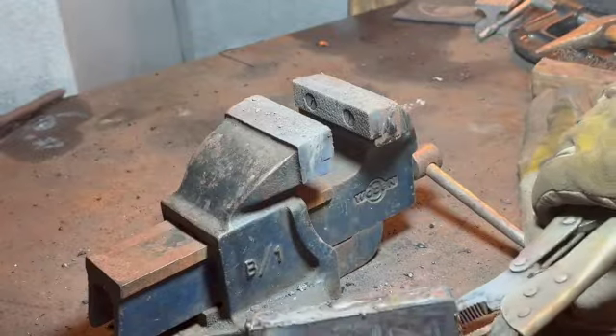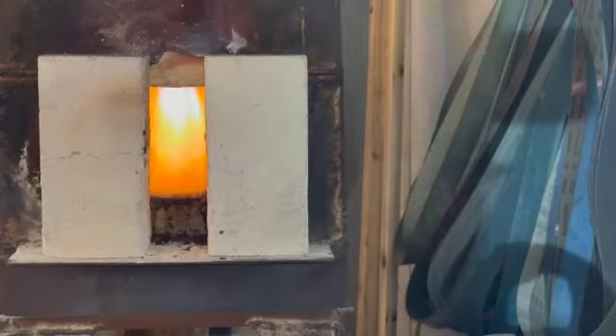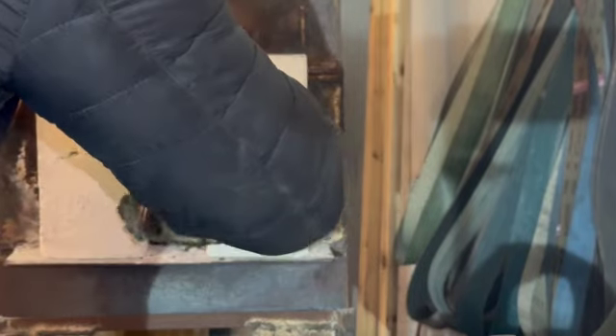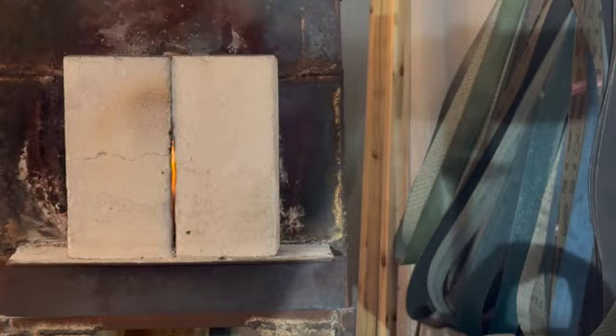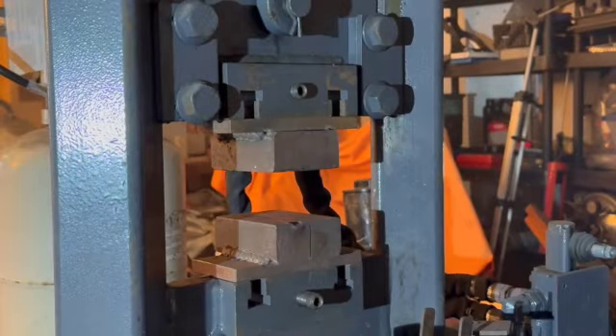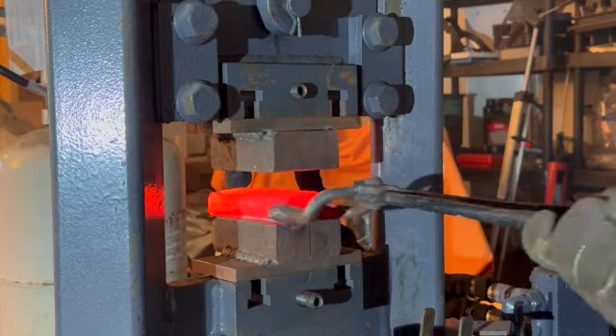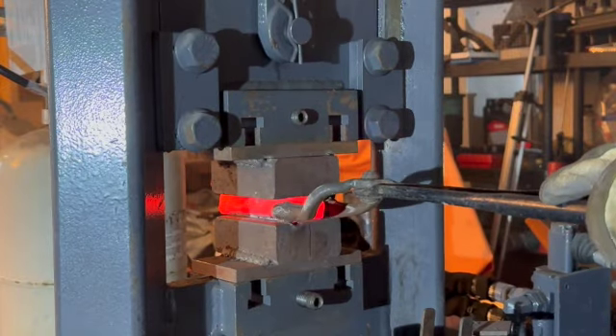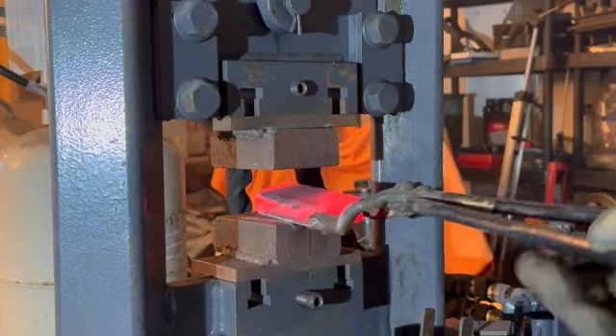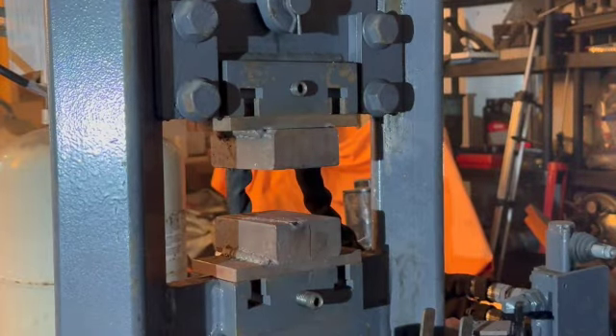I'll toss it back in the forge. It's small enough I'm just going to use tongs, so I'm not putting a handle on this one. And I'm really going to watch my temperatures. I want to make sure I don't liquefy that copper, but I want to make it soft enough that it actually brazes to the 1084 and the Damascus. Ideally, I'm looking to keep the temperatures between 1800 and 1900 degrees. I'll again do a quick pass to set the copper weld, if you can call it that, and then we'll start drawing it out.